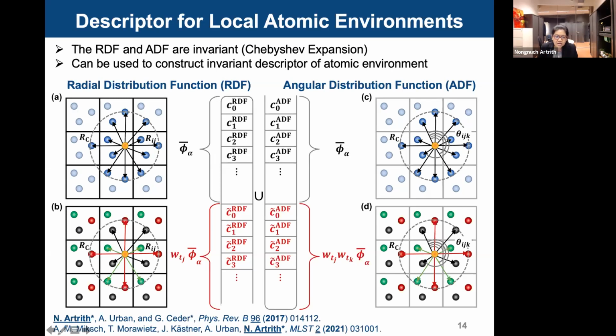So in the notation here, I use W's for the weight type of chemical species. If you have one chemical species in your system, we have 0 as a weight, so you only need to describe the structure only on the top. But if you have 2 chemical species, the weight type that we apply is -1 or +1. If you have 3 types of chemical species, you can use -1, 0, and +1, for example.